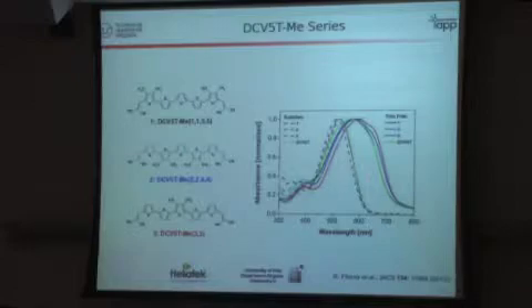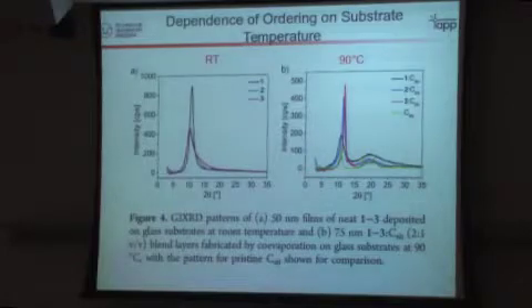The solid state spectra, as you see, are massively redshifted, which they should be. It tells you there's good coupling between the molecules. And here you see the differences become larger, and especially compound 3 has the largest redshift, which says it seems to have the largest packing. Now, when we looked at the ordering using X-ray scattering, it turns out that there's quite complicated behavior at room temperature. Compound number 1 has the highest ordering and the most clear reflexes. But at the temperatures where we usually deposit the solar cells, compound number 3 has the highest ordering. So those two results tend to show that compound number 3 seems to be the compound of choice.